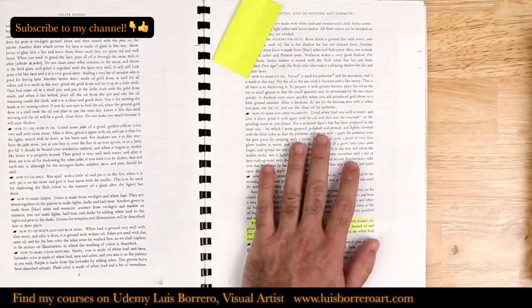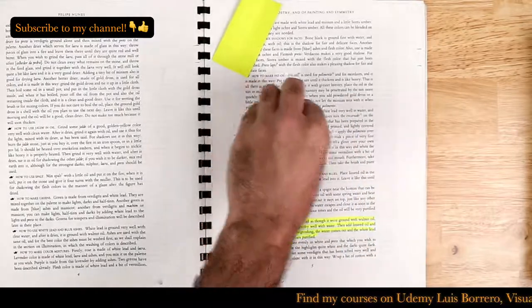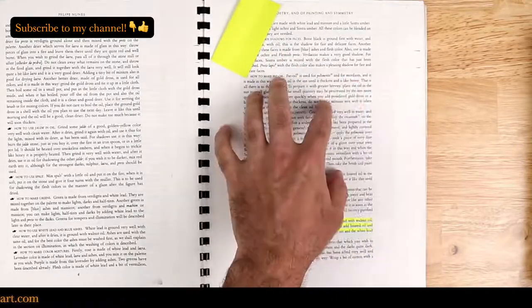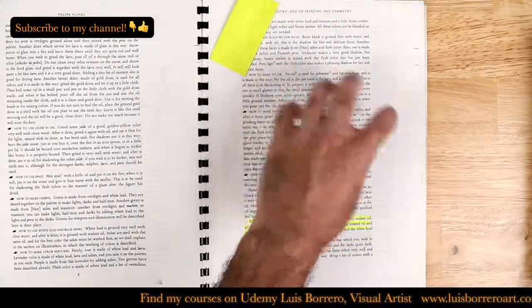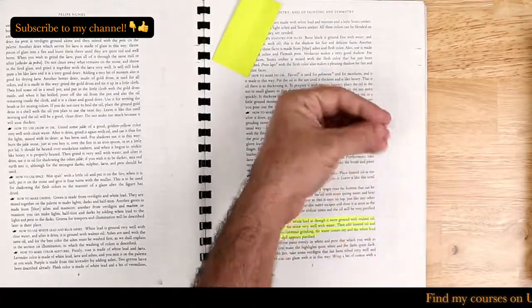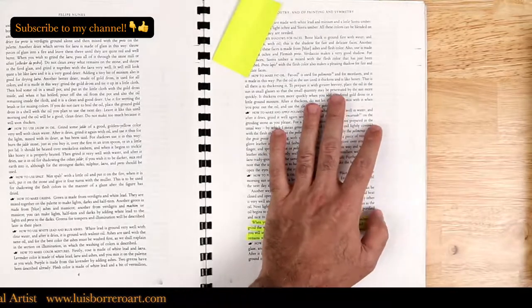Oh, I see. Okay, Ron. So this is not lime. This is lead white, but lime was used as the other white. So in this recipe, with the lead white, you can combine the calcium carbonate with the lead white, and the Dutch called it loodwit, and it's essentially a cheaper, more inexpensive type of lead white. So by combining the two available whites, you get a superior white essentially, because the lime or the calcium carbonate will make it slightly transparent, and it will create a neutral environment in the acidic oil.